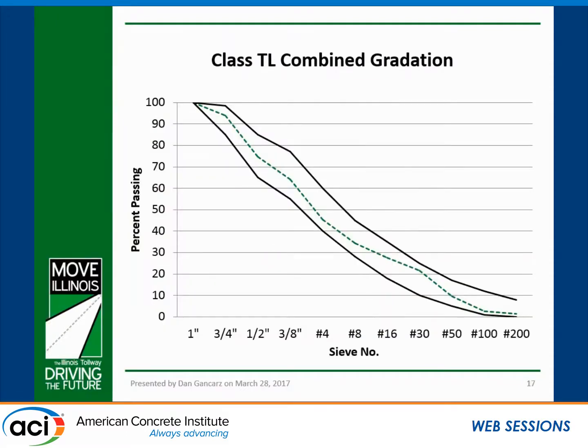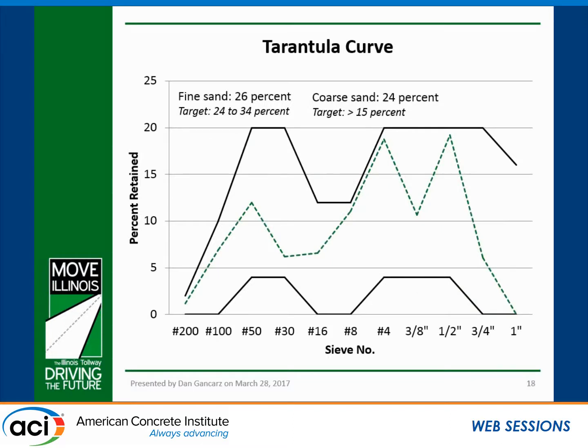So for our TL spec, we also have a combined gradation requirement. So the black lines are the requirement. The dotted green line was how this mix ended up, so pretty well graded. Also plotted this on the Tarantula Curve, which I think is part of the new AASHTO spec. So it falls well within the Tarantula Curve, also meets the requirements for fine sand and coarse sand, which is better than what we've seen in the past with a lot of our mixes that are gap graded or just not optimized properly. We'll commonly see a spike up around the half-inch sieve. So this mix, they really took the time to look at the overall grading and make it well graded with the materials they had.